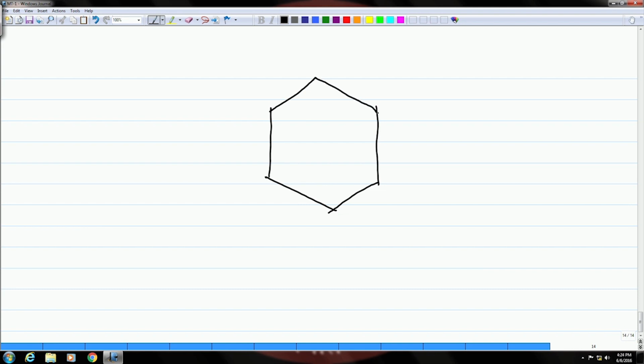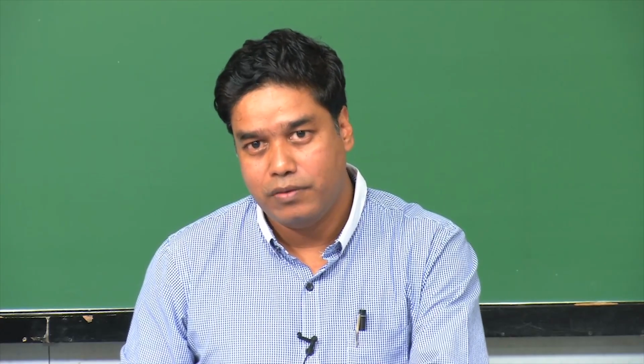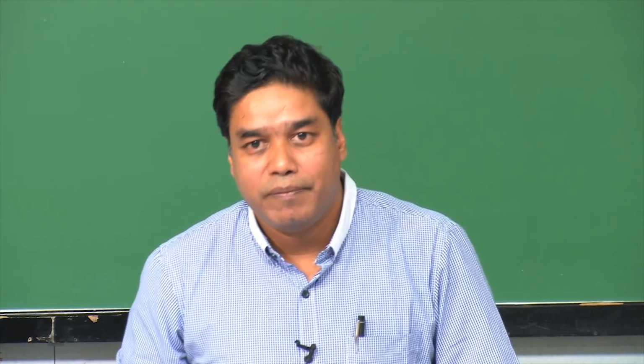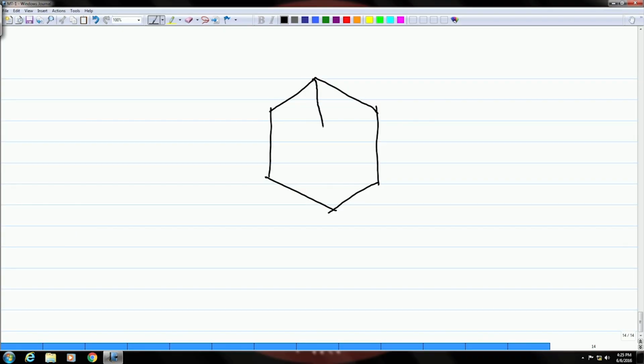Like this. So, this is what you will see on the other side of this pie gauge. There is no slot or anything on this surface. Okay. So, you keep this upside down, that means the slotted side will be down, and then magnetize. Once you magnetize and then start applying the particles, you will see some of those slots being indicated like this on the other side. Okay, like this you would see.